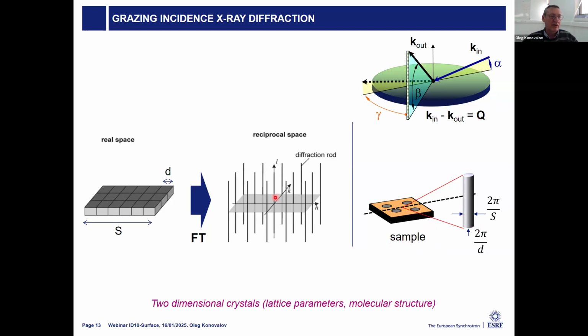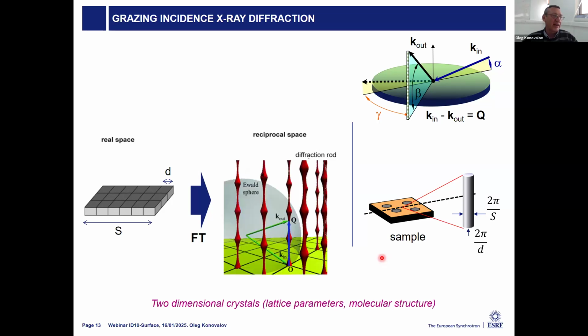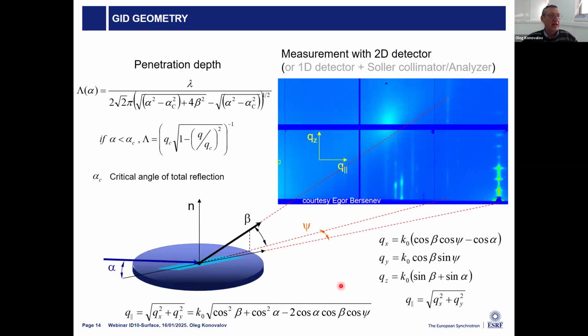From the position of these rods, we know the lattice parameters. From the length of these rods, we can see the thickness of this crystal in that direction. And from the width of these rods, we can see the correlation length of these systems. If this is not really two-dimensional, but a bit of a third dimension appears, then we can also see that on these rods we have some other Bragg peaks which we can measure. So then we see information in the third direction, how it is organized structurally, if this is a crystal. And this is one example of real measurements.